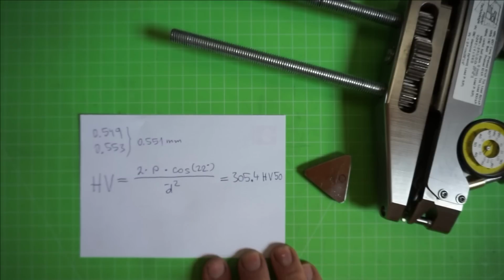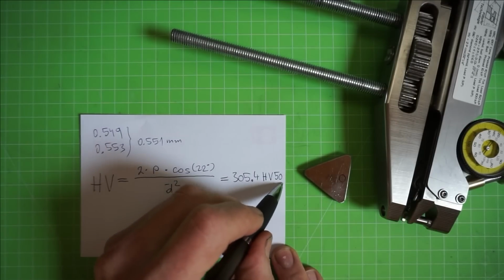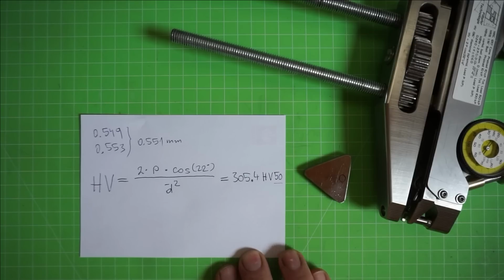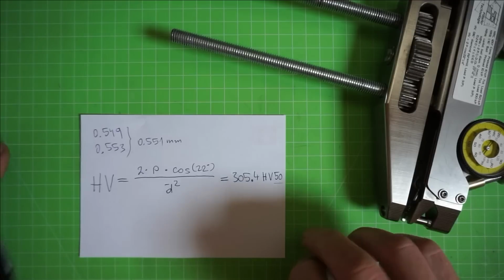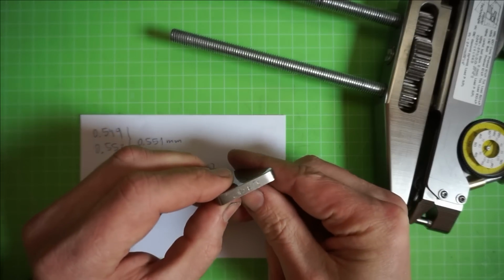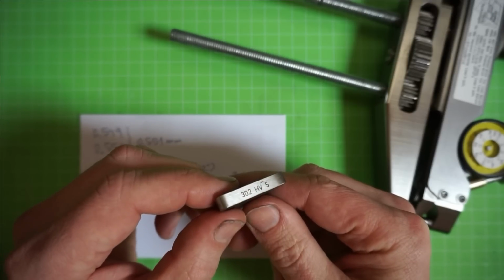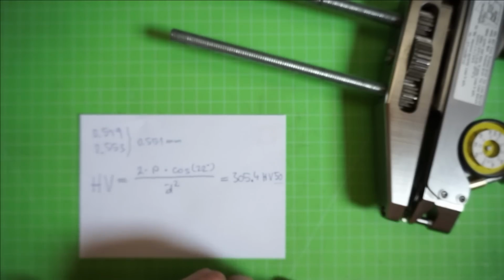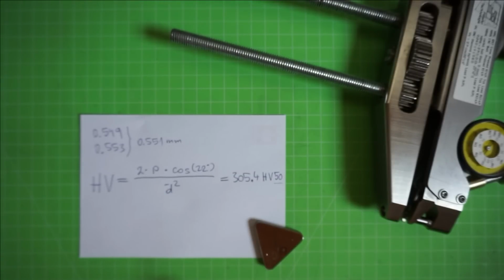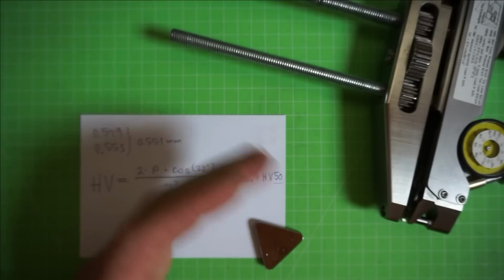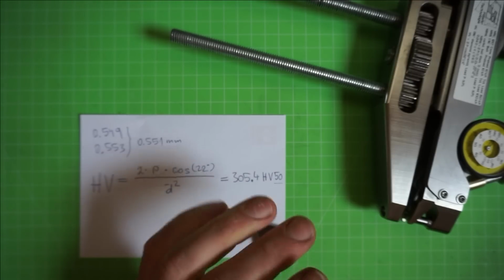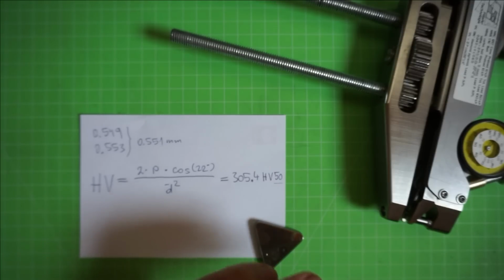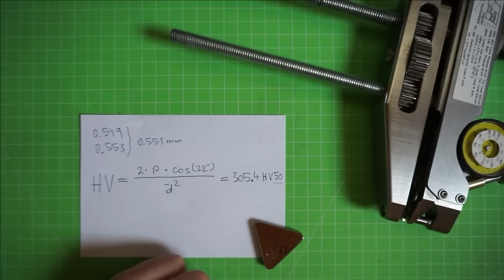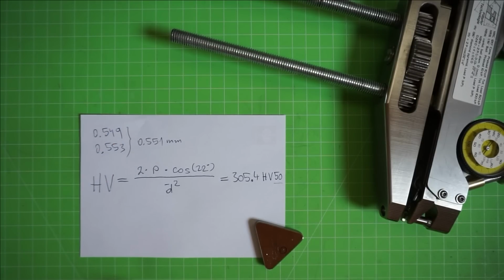HV50 is the unit that we have to specify, because we used a testing load of 50 kilograms-force. And considering that this comparison plate has a rated hardness of 302 Vickers, and keeping in mind that the Vickers scale ranges from 0 up to above 1,000, then this error is really quite alright for my purposes. When you use smaller loads, the errors might get as large as, I don't know, plus or minus 50 Vickers, even with the best testing machines.